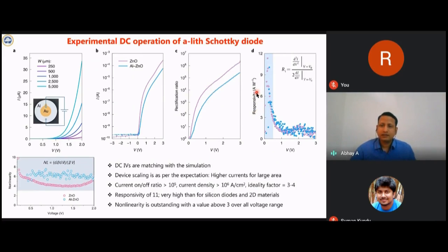So the responsivity, and its unit is ampere per watt, is maximum close to zero bias, and its value is around 11. So this value of 11 is very high compared to silicon diodes, and its thermodynamical limit is actually 19. So there are not many diodes which can show this kind of responsivity. In the previous case of that MoS2 example, the responsivity was of the order of 6 or 7.